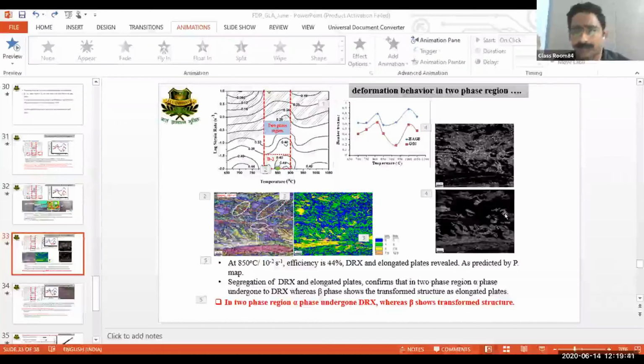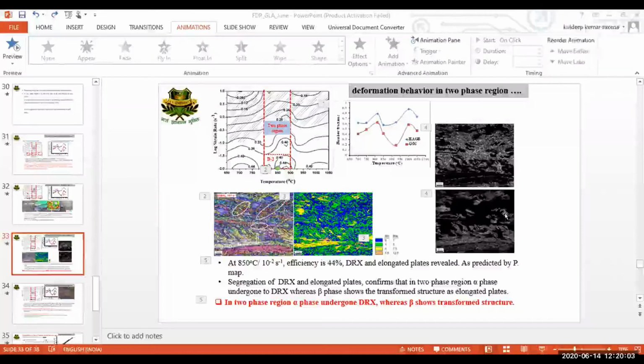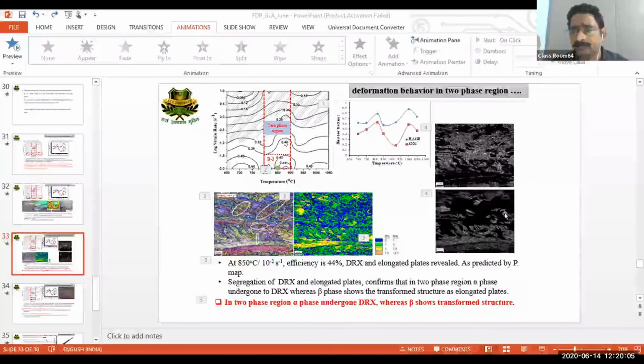You will be very clear how we can get an idea from the flow stress and flow strain curve. Because normally in the case of hot deformation, we have three kinds of flow behavior. One is known as strain hardening, another as steady state, and the third as flow softening. Steady state normally predicts the DRV, but when you have flow softening, meaning your curve starts decreasing after the peak, then you can assume DRX may be existing in the deformed microstructure, but it is not sure that only DRX is existing.